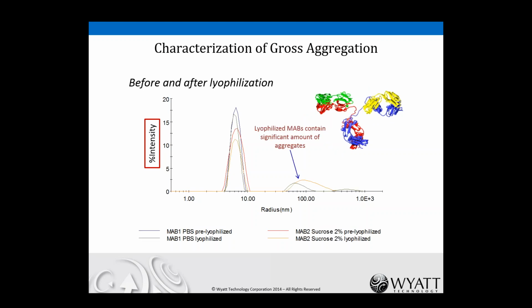So after reconstitution, we find the formation of these large aggregates at around 100 nanometers in radius. And in this case, the sample with the sucrose had larger aggregates, but you can see some really large aggregates in the sample without the sucrose. That's right up here. Even though these are actually very tiny quantities of aggregates.